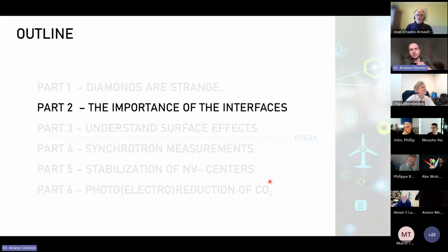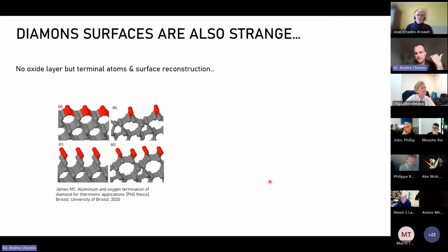In this section, I would like to make you understand how important the interface of diamond is. As I said, when you cut the diamond, you have to terminate it. In many semiconductors, like for instance silicon, the silicon will tend to end with an oxide layer, silicon oxide, a few nanometers or tens of nanometers thick. In diamond, it's not the case at all. You cannot have an oxidized surface of diamond. I mean, you can have an oxidized surface, but it's not an oxide layer. It will actually be oxygen atoms that bond to the carbon atoms at the surface, just like in that picture. And those terminal atoms will behave similarly to small molecules.